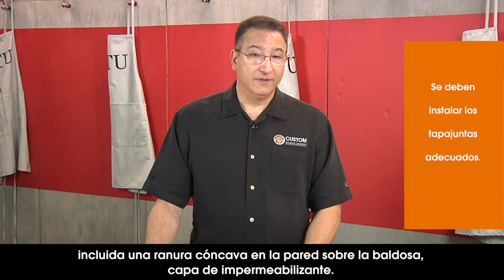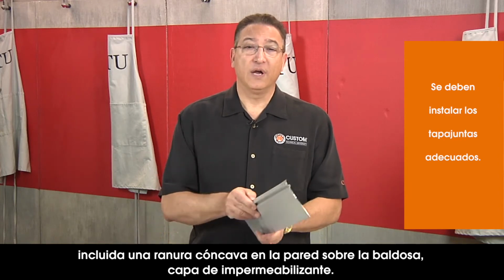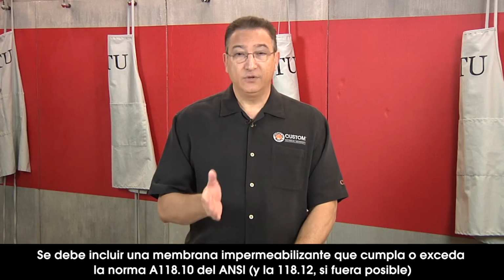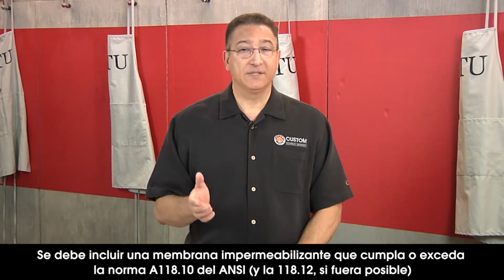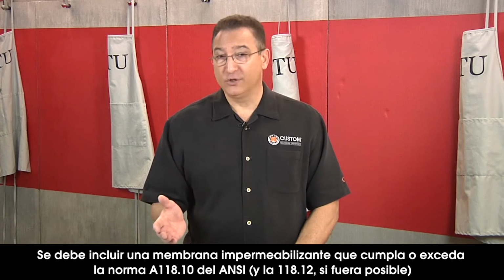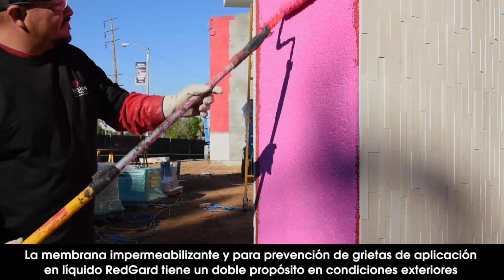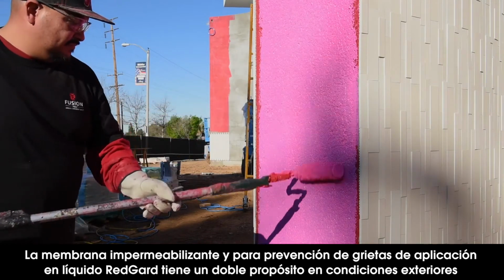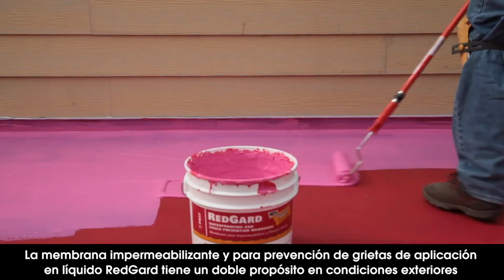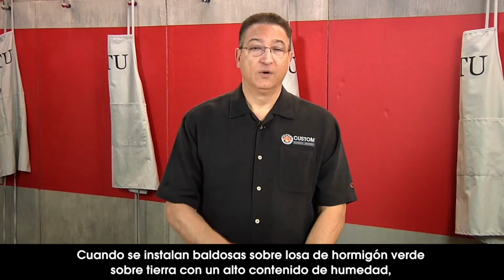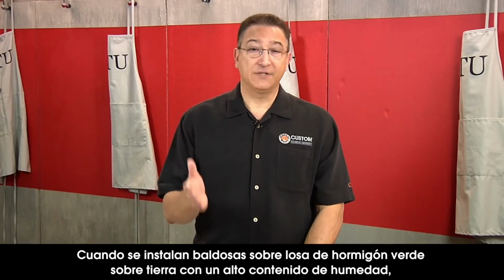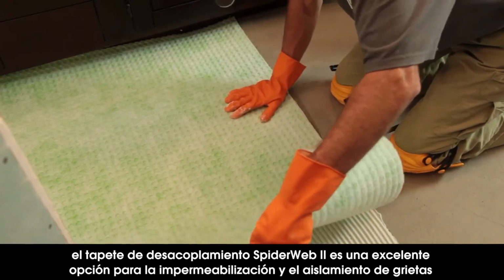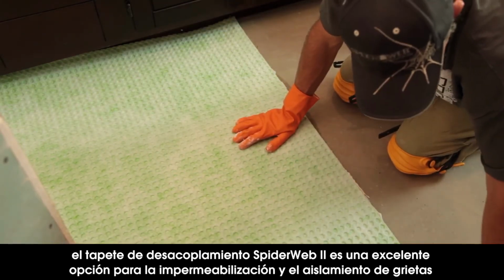Proper flashing must be installed to prevent seepage, including a cove reglet embedded into the wall above the tile, mortar, and waterproof layer. Include a waterproofing membrane that meets or exceeds ANSI A118.10 and A118.12 if possible. And it also has to be rated by the manufacturer for these types of applications. Liquid applied RedGuard waterproofing and crack prevention membrane serves a dual purpose in exterior conditions, protecting both the tile and the structure. When tiling over a green concrete slab that has high moisture content, Spiderweb 2 uncoupling mat is an excellent choice for waterproofing and crack isolation.